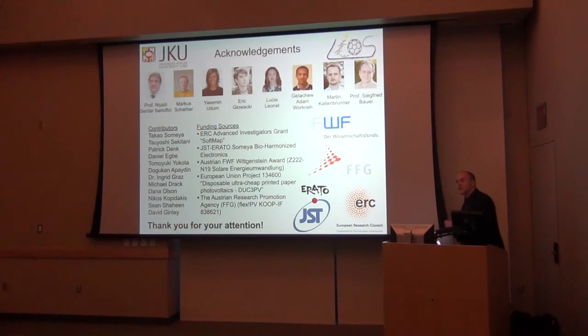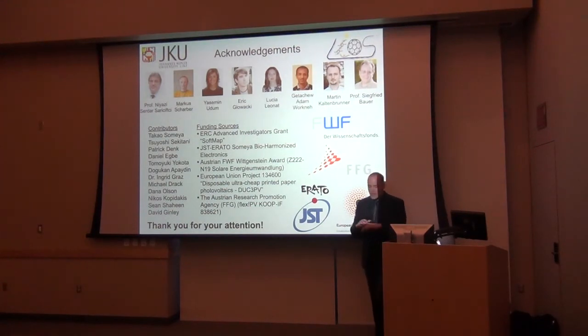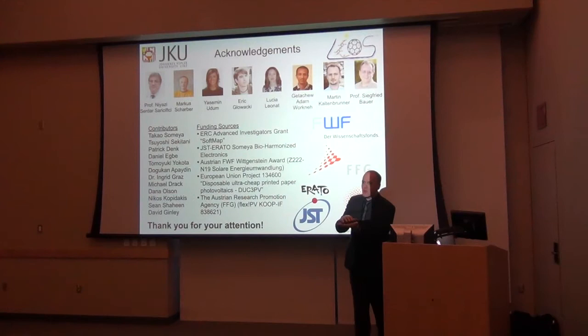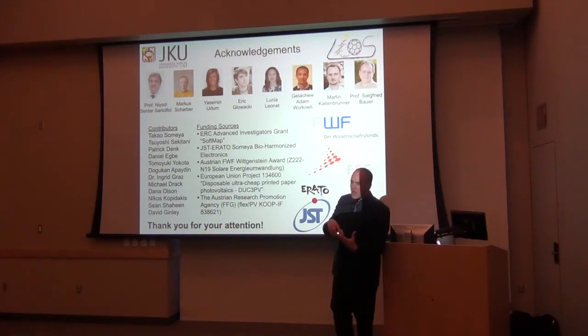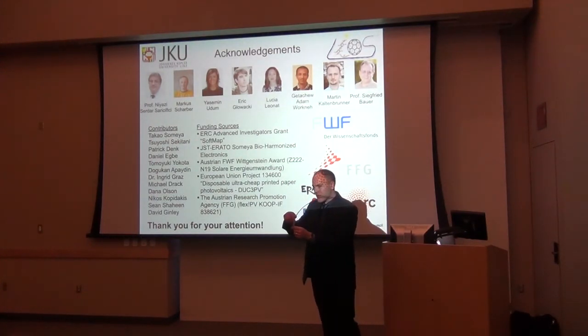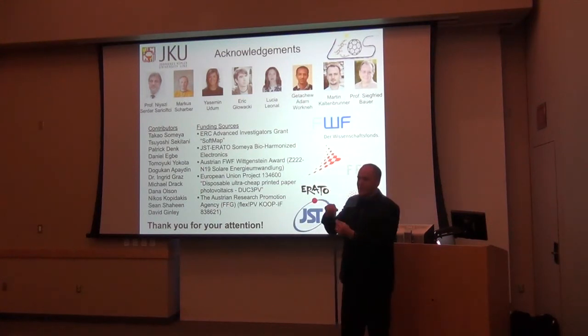This last part of this material ended up with a solar cell that wasn't very efficient. So why wasn't that? The reason it wasn't very efficient is because these things form big crystals. And we're trying to make thin film devices, and you have two contacts with something that doesn't form a nice film. You have big crystals with holes in between. And so you're limited by the shunt resistance from having the two contacts that touch each other directly, in parallel to the actual crystal itself. That's one of the reasons.